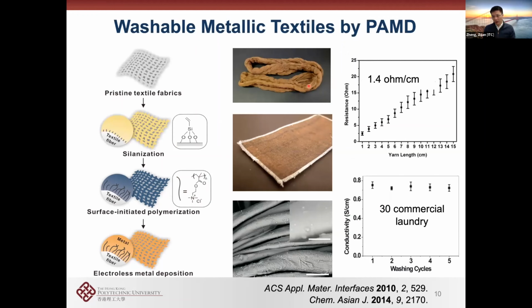We can get copper yarns and fabrics, and if you zoom in, you will see that on every single cotton fiber, a thin layer of metal, in this case 300 nanometers thick, is conformally coated on top, no matter how the structure of the cotton looks. Cotton is typically very irregular, but despite the topography, you can coat a nice layer on top because the growth was from the bottom up.